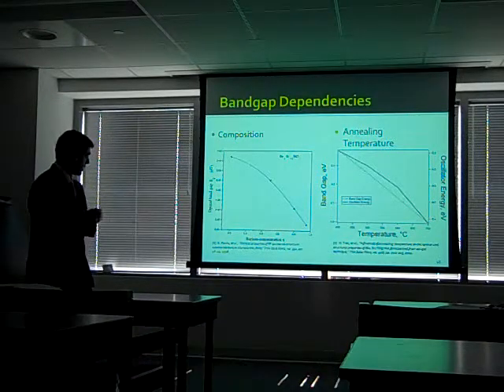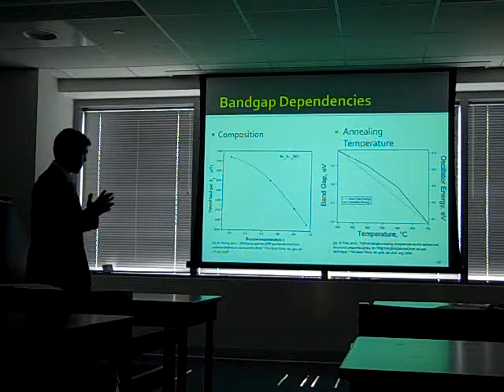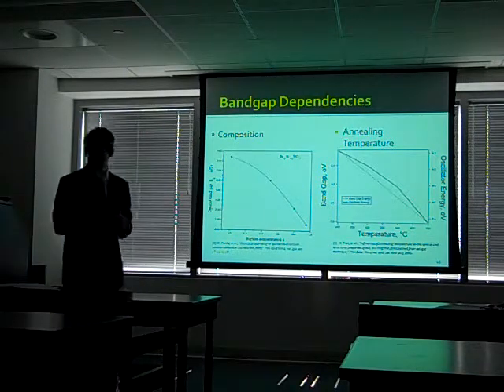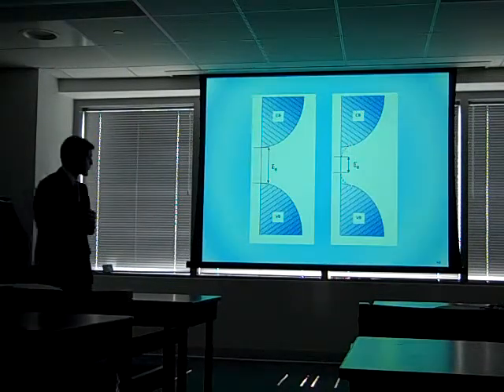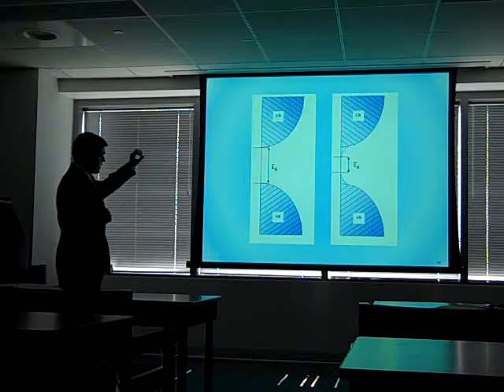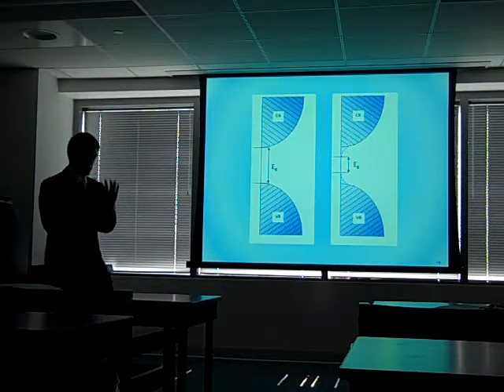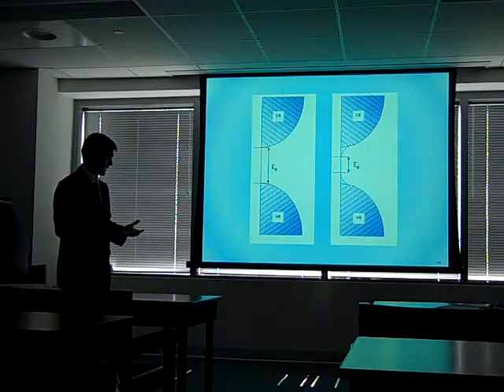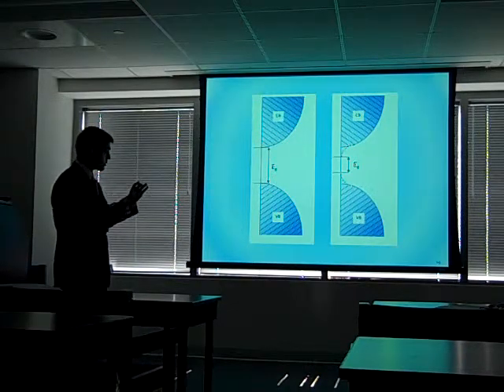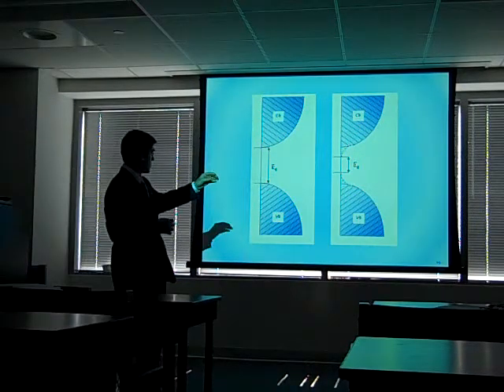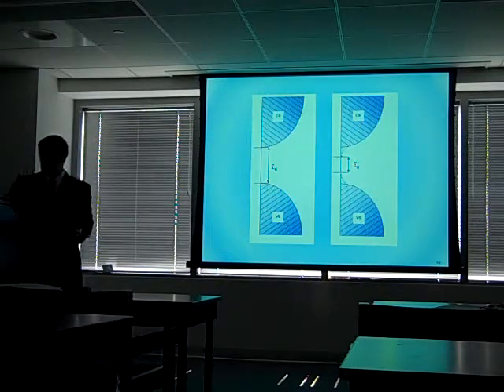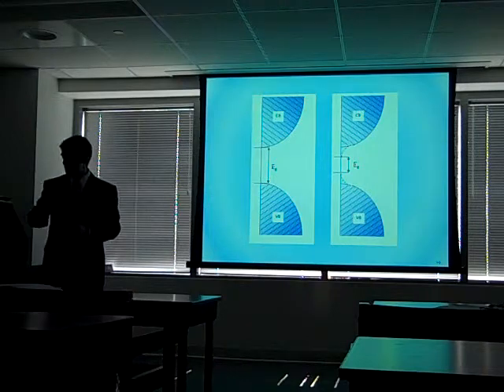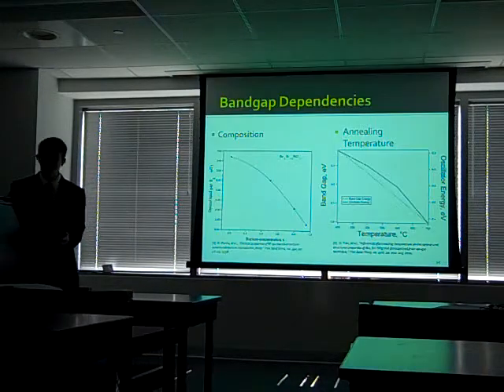So if we can identify the fundamental band gap of the sample, then we can identify a concentration. However, I just want to point out that the fundamental band gap is going to be the indicator, but due to the presence of defect states, the model can be thrown off, and sometimes the model band gap isn't quite the fundamental band gap, and so we have to understand what causes these defect states.